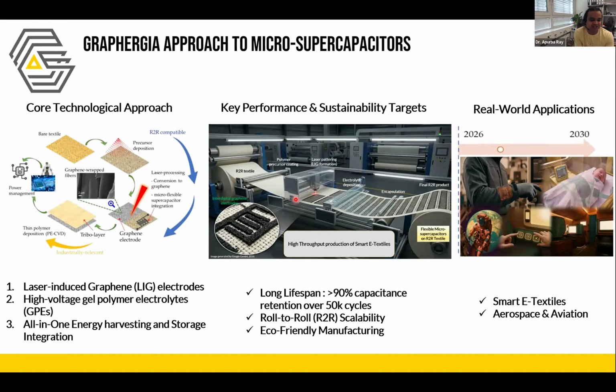relies on three distinct pillars. I would say there's laser-induced graphene electrodes, and this graphene uses dry processing or one-step processing that totally eliminates chemical or any other harsh chemical reduction process, and this high voltage gel polymer electrolyte that eliminates the leakage problem and the flammability problem of traditional aqueous electrolyte or liquid electrolyte, and finally